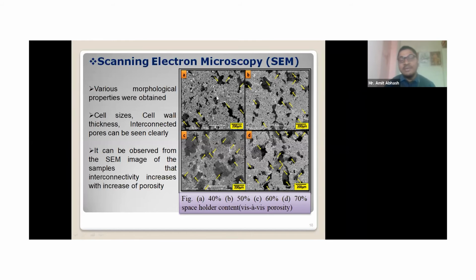of porosity. We can see that, as here you can see in the first image A, there are less interconnected pores, less interconnectivity among the pores, as this is 40% porous, 50% space holder I have used here, here 60%, and here 70%. So you can see more interconnected pores in case of 70%. And as we are increasing the porosity, the interconnectivity among the pores is increasing.